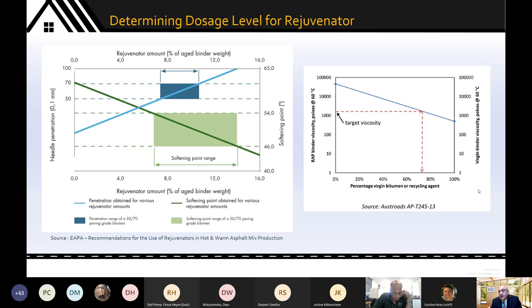some states use liquid binder testing. And in that case, they tend to focus on PG high grade and PG low grade. Some people target the rejuvenator dosage based on high grade, and some people target rejuvenator dosage based on low grade. Both these are acceptable. It generally turns out that if you target the high grade, the high temperature properties like softening point or PG high grade versus a low temperature property, let's say like a frost breaking point or a PG low grade, in general, if you target the high grade to determine your rejuvenation content, you tend to overestimate the amount of rejuvenator needed for the actual mix.